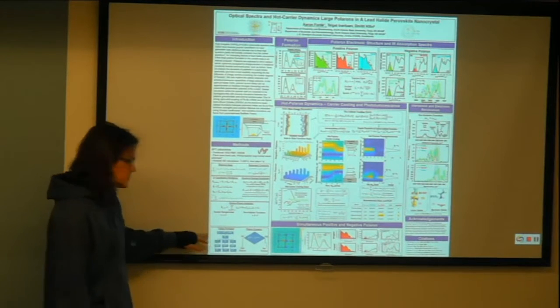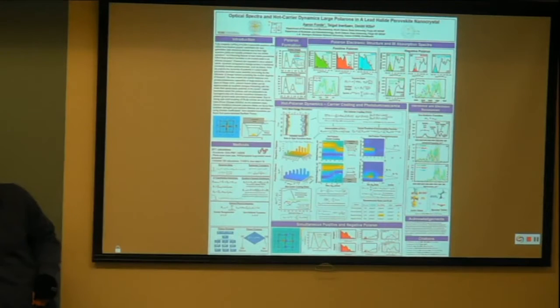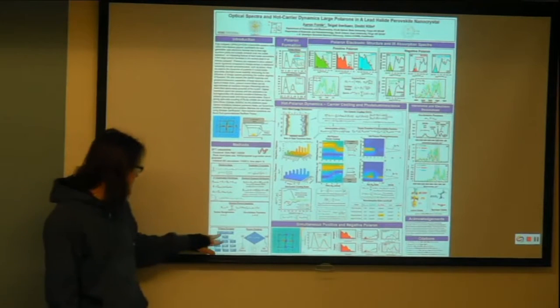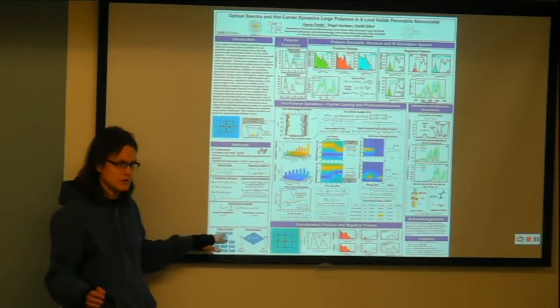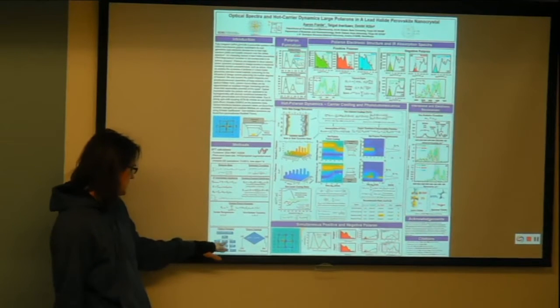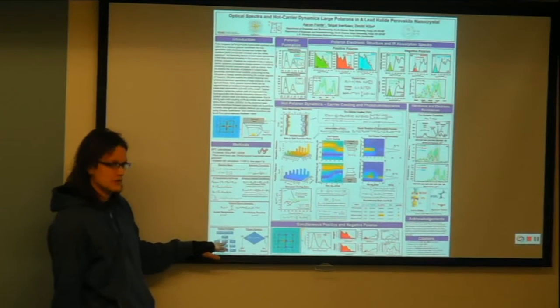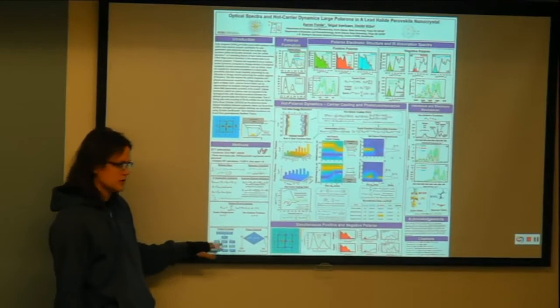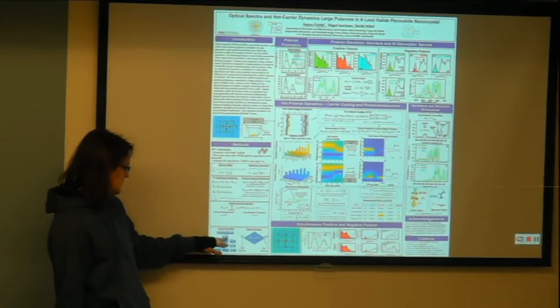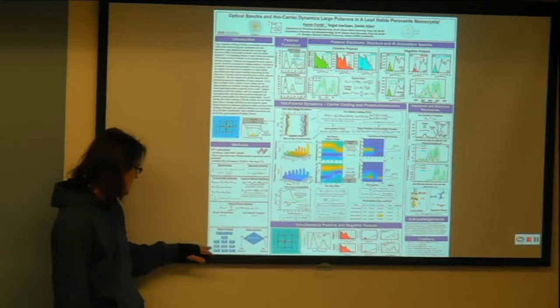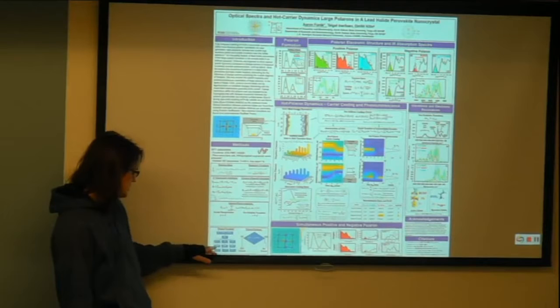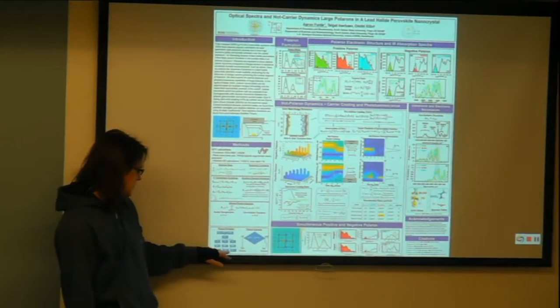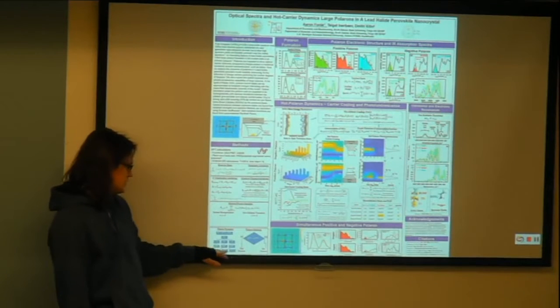And so this is just kind of a flow chart to illustrate how we process the models. For each model, there's an equilibrium number of charges, which would be adding or removing 0 charges, whereas to induce polaron formation, we either add or remove charges. So we start with our model, consider how charged we want our polaron, choose the charge state, put it into DFT, and then for each charge, there'll be a specific change in the nuclear coordinates. So we use delta R's.